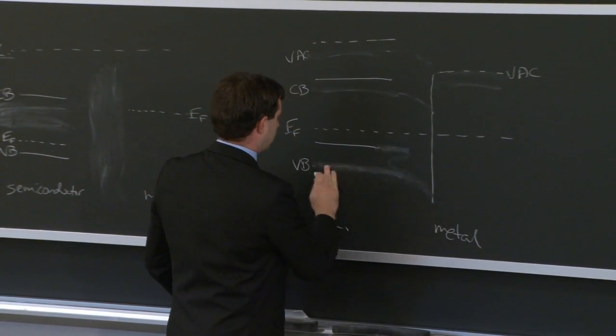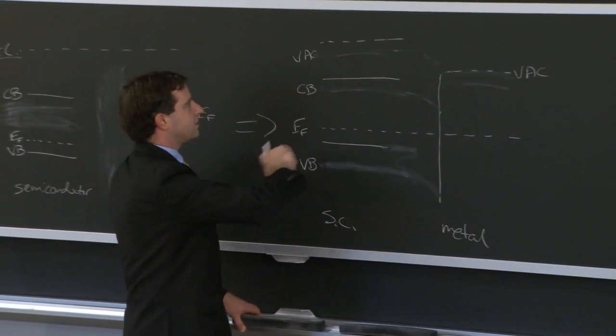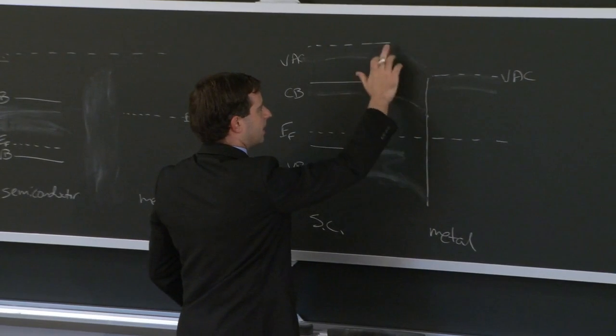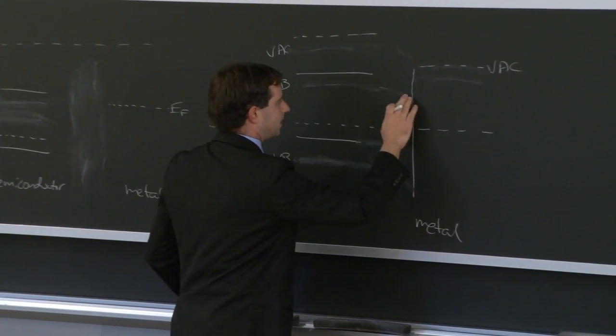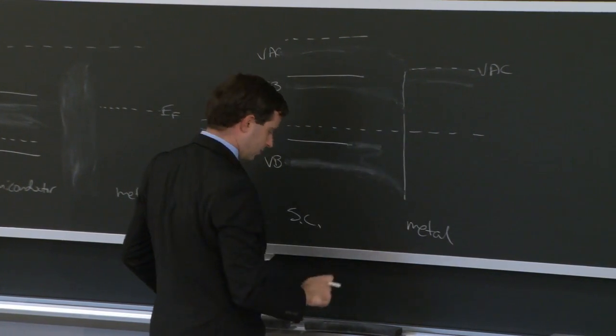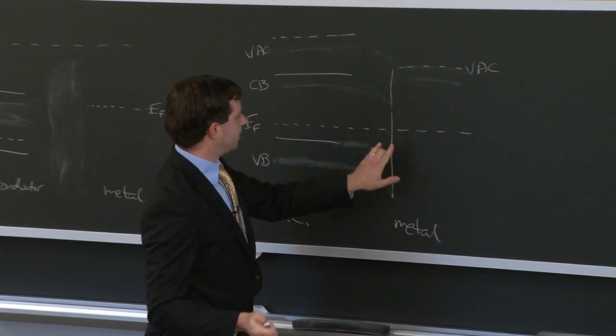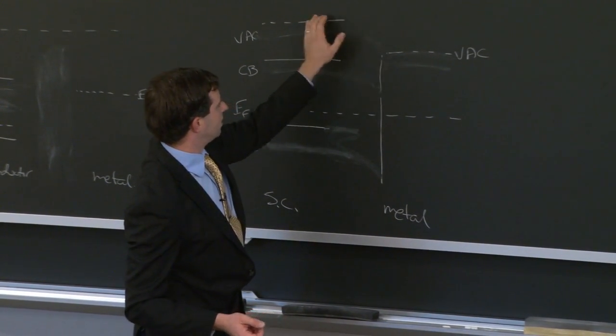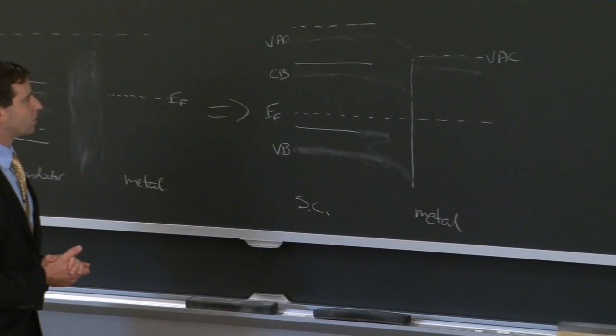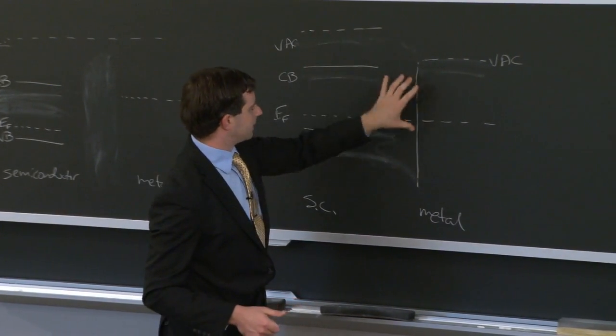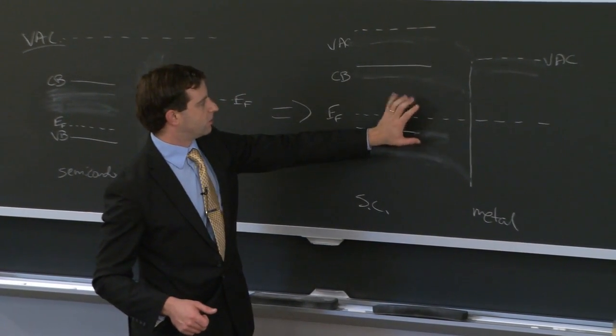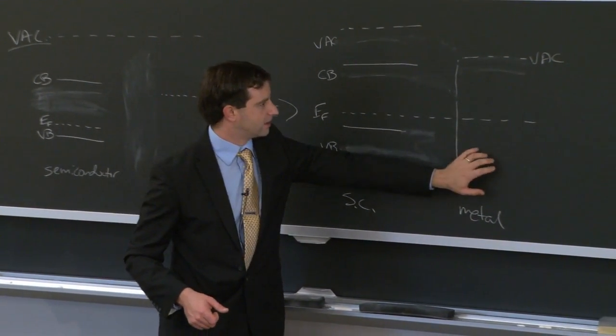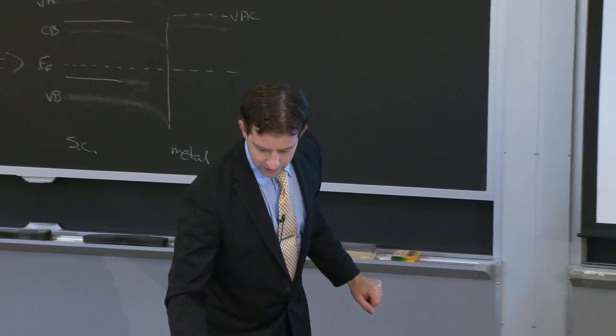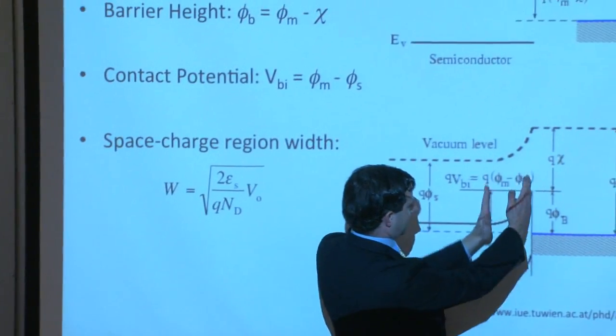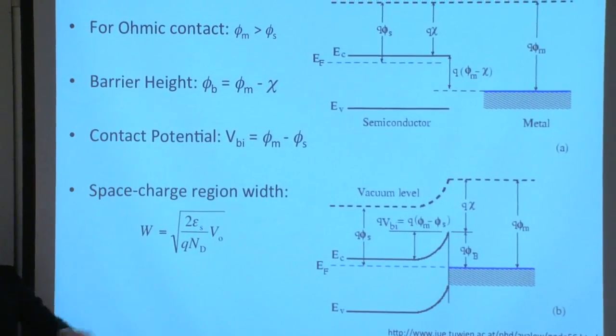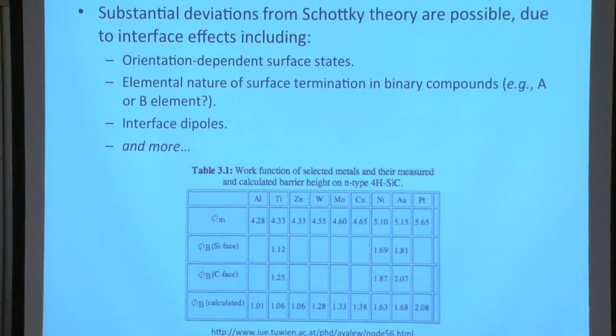Excellent. And now, again, just going through the logic of the process here, we have to make the vacuum levels match. And there's going to be an equal amount of charge on either side of that junction. Now, when there's a charge, there's a field. When there's a field, there's a potential, and the potential will be manifested in the bending of those bands approaching the interface. The bands will bend a lot more in the semiconductor than they will in the metal because the free charge density in the semiconductor is a lot less than it is in the metal. And going back to this equation right here, the width of the region of bent bands is going to depend inversely on the dopant density, or the amount of charge in that region.